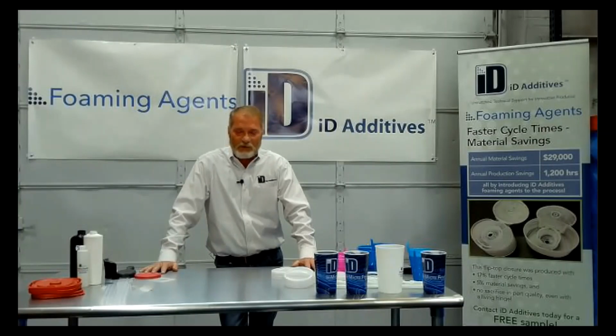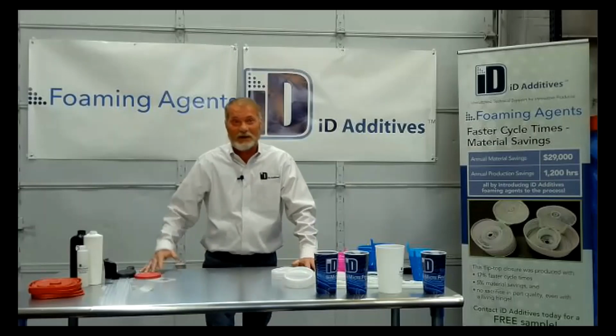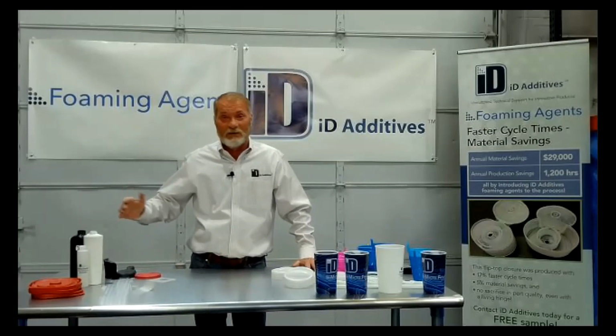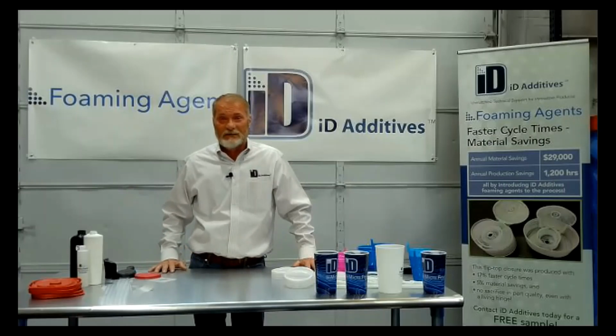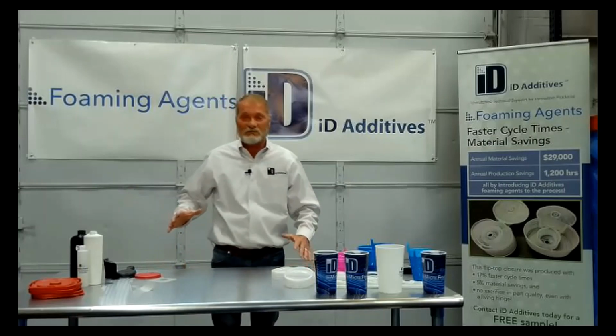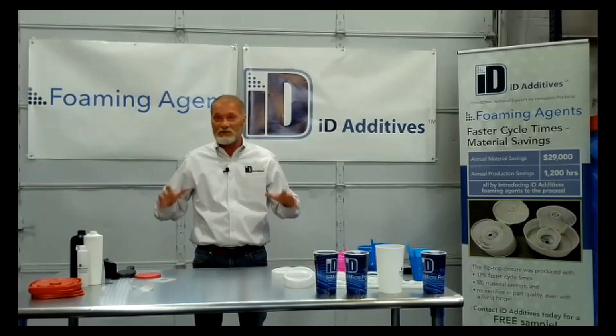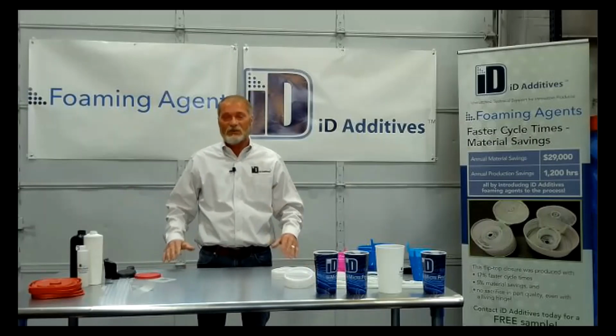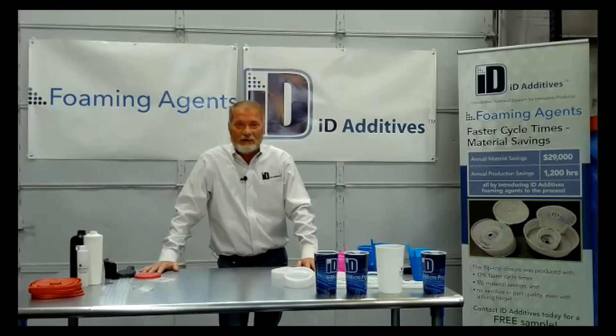But what's important is that recovery time and that residence time. You always want to keep that material moving. You don't want to leave it set back for a long time. You don't want it sitting back there waiting for the mold, because you will lose a ton of gas. Just by slowing your RPM down alone, that will make a huge difference in your product and how much gas you get into it.